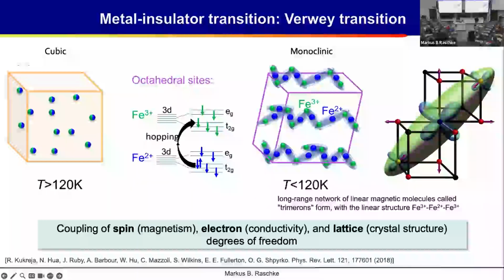And this in general has been a very important and foundational principle, that we have a coupling of the lattice structure, so the position of the atoms, with the electrons, and the electrons are responsible for the conductivity. And then further, and this is not shown here, this spin order is also temperature dependent, and so we have a coupling to these spin degrees of freedom. And this is the foundational principle of what's called correlated quantum materials, which is this interaction between the spin, the electron and the lattice properties. And this determines in complicated ways many of these quantum phenomena, including superconductivity. We'll talk about this a little later, and many other coupled electron, lattice and magnetic phenomena.